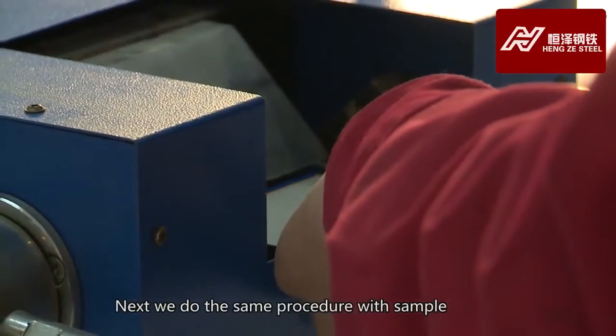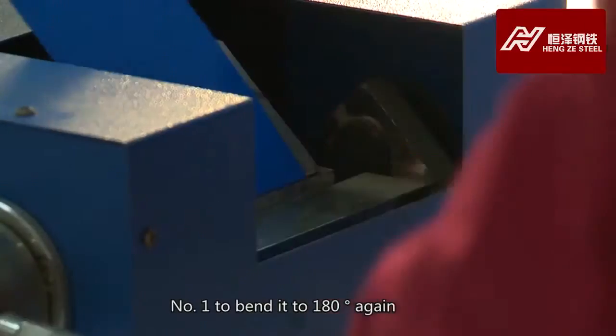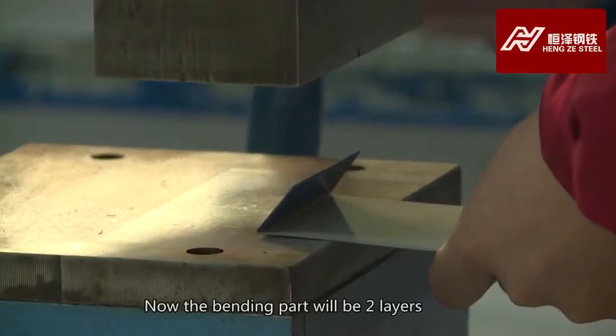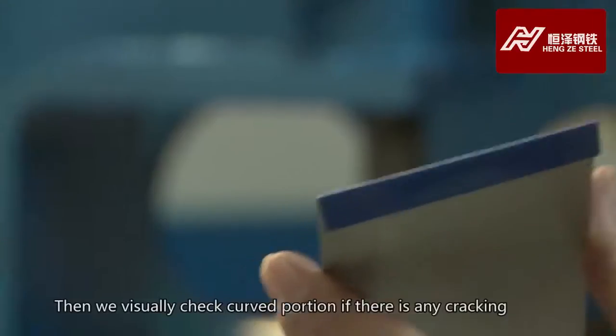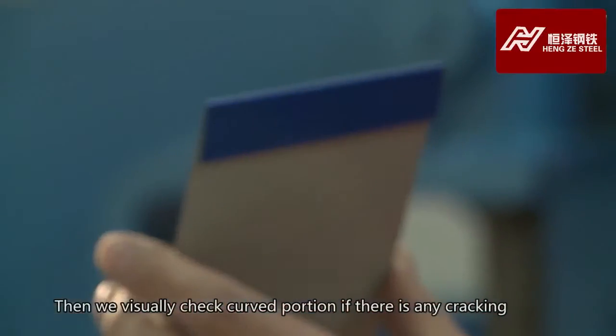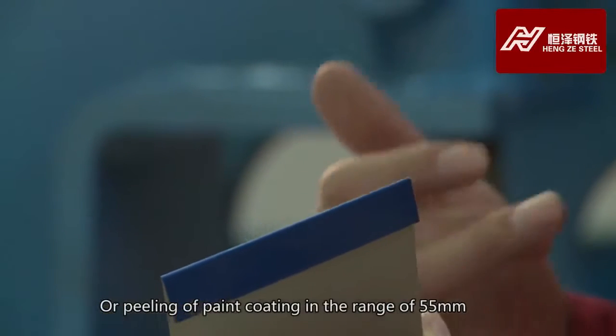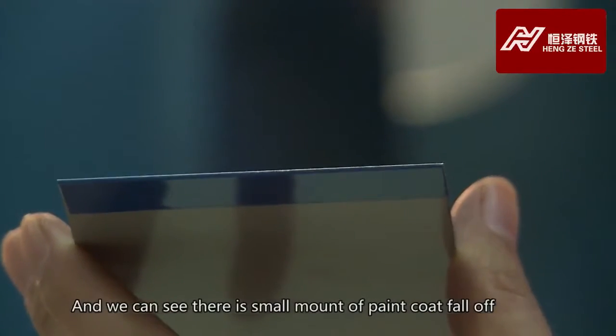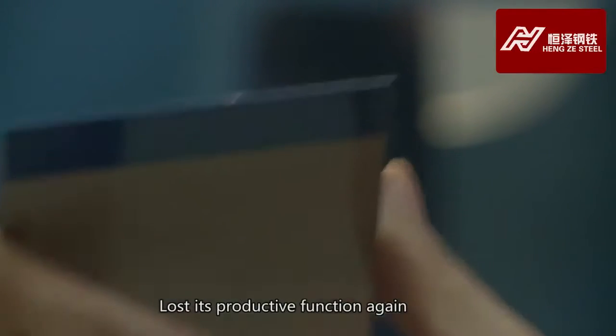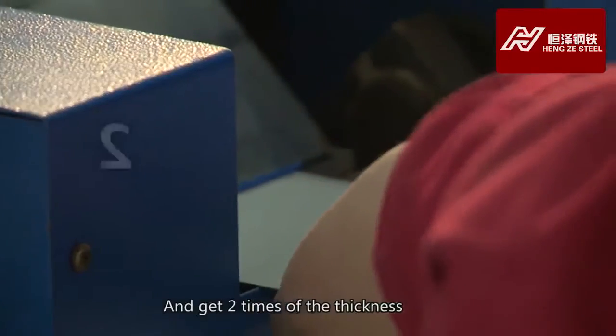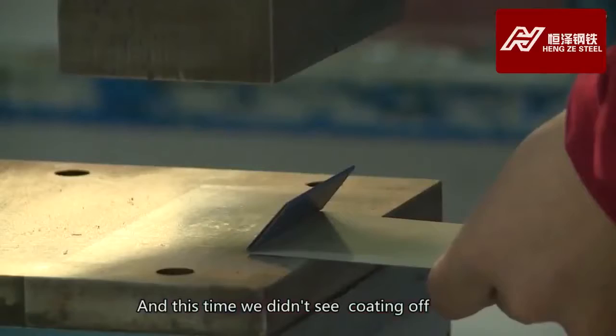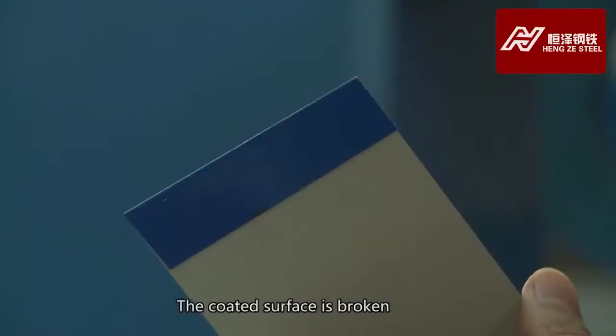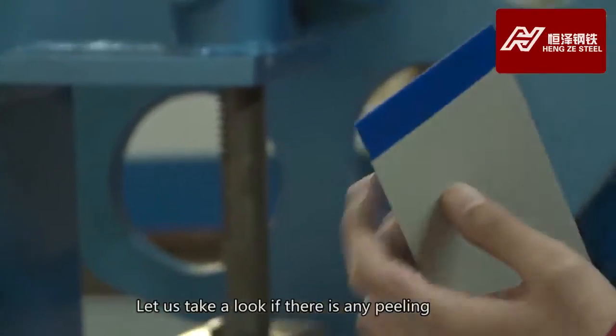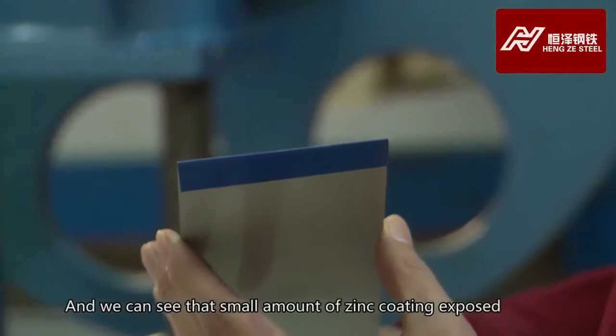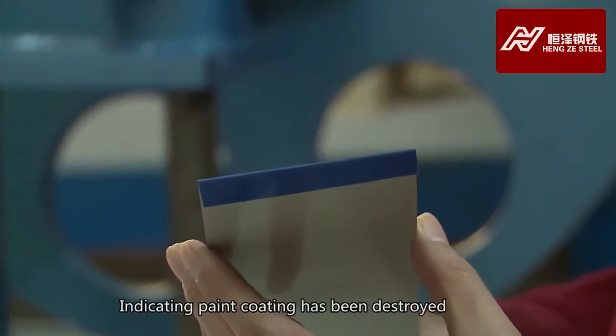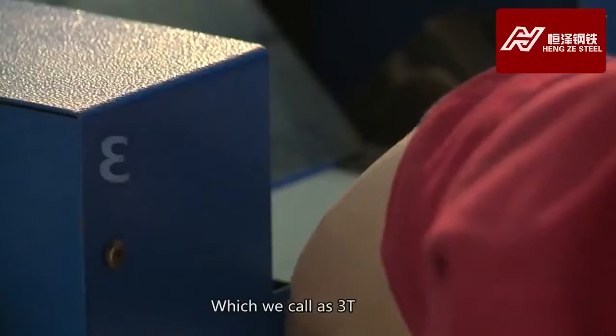Next, we do the same procedure with sample number 1 and bend it to 180 degrees again. Now the bending part has 2 layers, which we call 1T. Then we visually check the curved portion for any cracking or peeling of the paint coating in the range of 55 millimeters, and we can see a small amount of paint coat has fallen off, losing its protective function again. Then we bend with 2 times the thickness, which we call 2T. This time, we didn't see the coating come off, but looking carefully, the coated surface is broken. Let us take a look if there's any peeling, and we can see a small amount of zinc coating exposed, indicating the paint coating has been destroyed and lost its protection function again. Then we go to 3T.